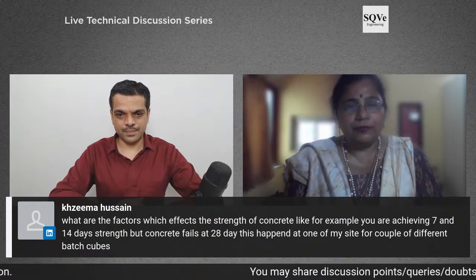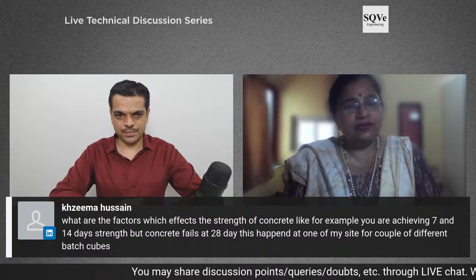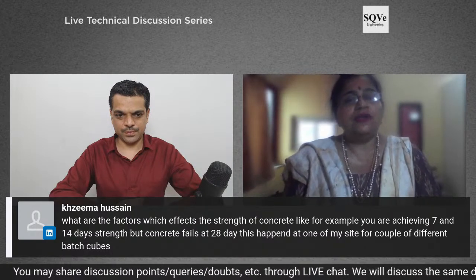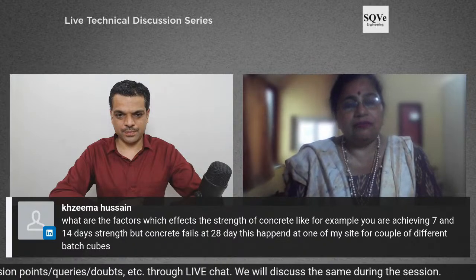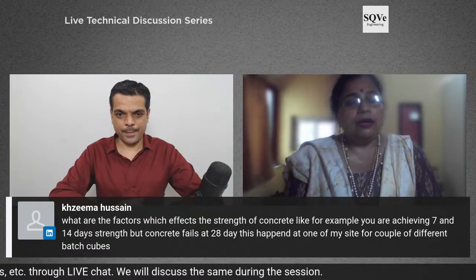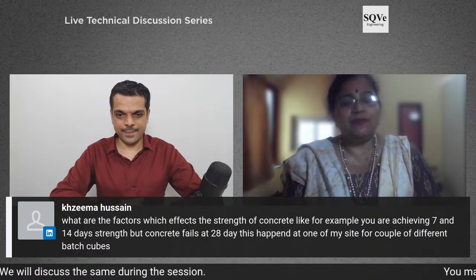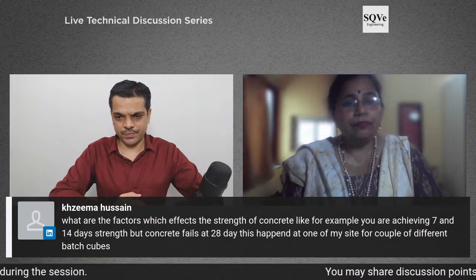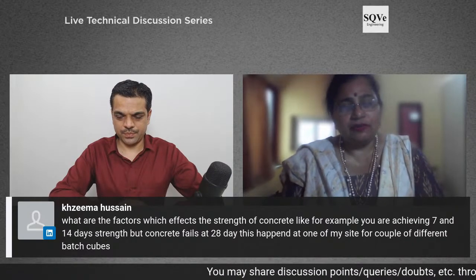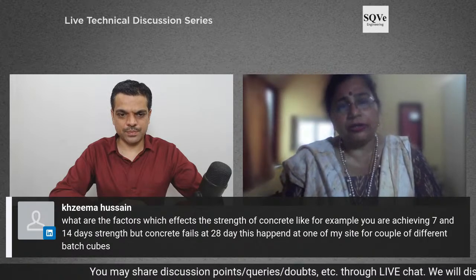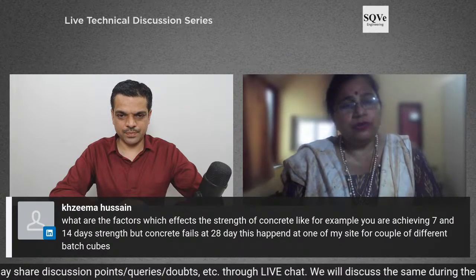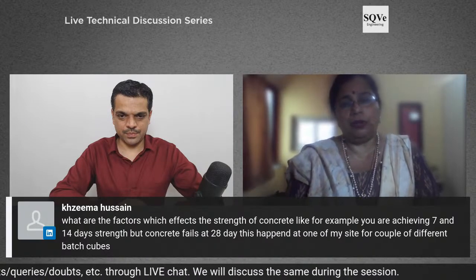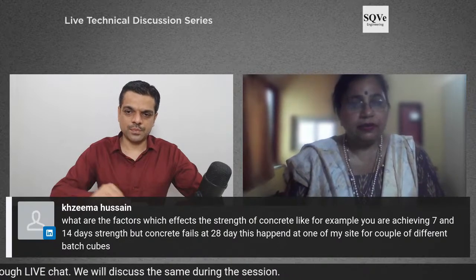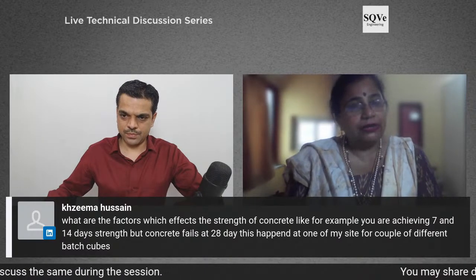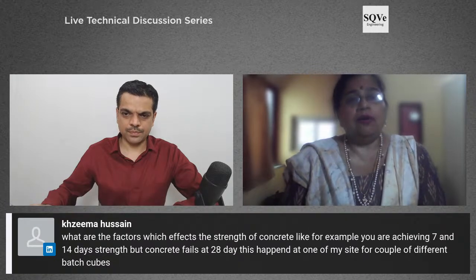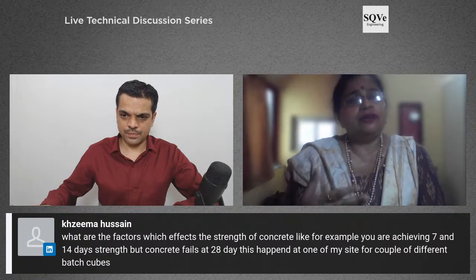So if we have confidence that the 7 and 14 day strengths were good or acceptable, as a consultant, and something failed at 28 days, there could be multiple reasons. One could be that the cube was not cast well, the workmanship itself was wrong, or maybe the curing was not done enough, or the cube molds were incorrect, or maybe the machine itself was not properly placed. There are different kinds of issues that can arise.